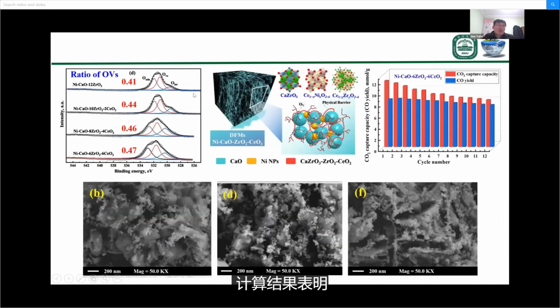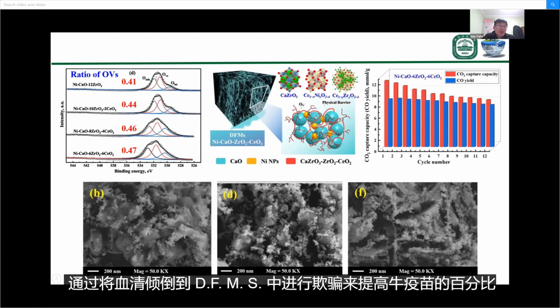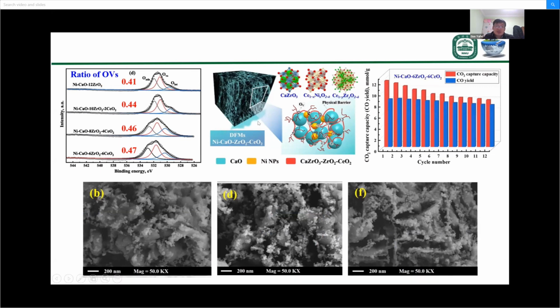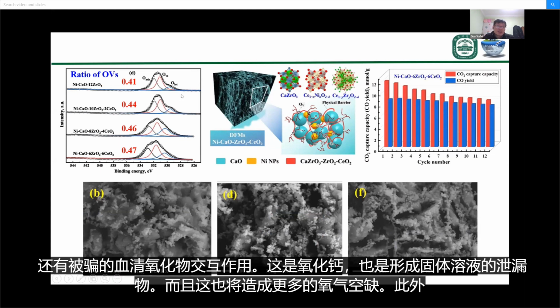And the calculation results reveal that by doping the cerium into the DFMs, the percentage of oxygen vacancies increases, and the doped cerium oxide interacts with the calcium oxide and also the zirconium to form solid solutions. And this will also create some more oxygen vacancies.